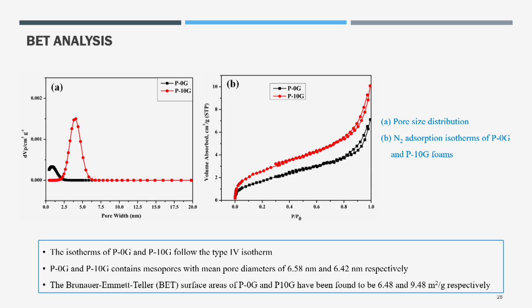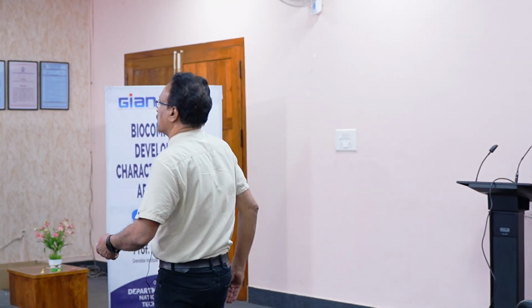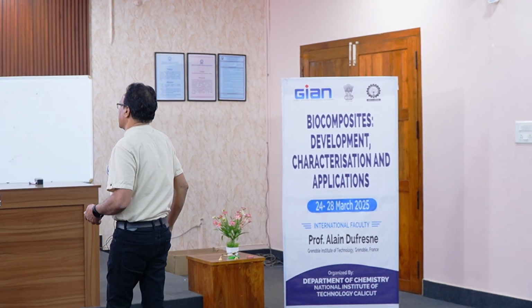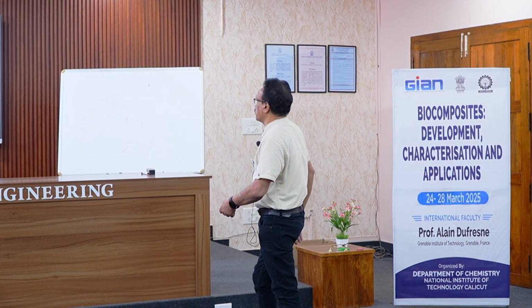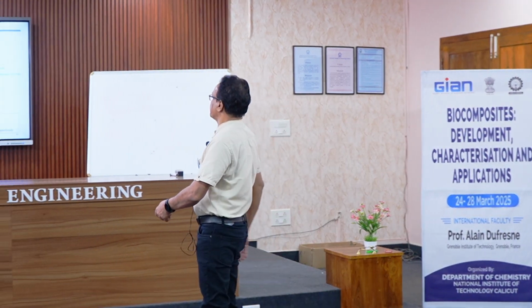How many pores are there? If the pore size is 2 to 50 nanometers, it's called a mesopore. If the size of a pore is below 2 nanometers, it's a micropore. 2 to 50 is a mesopore. Above 50 nanometers, it's a macropore. All the values run between 2 and 50. Therefore, on average, the system contains mesopores. So it's a porous system. That's why we called it a foam. It's a light substance containing a large number of pores. And the BET examinations tell us that the surface areas are 6.48 and 9.48 respectively.